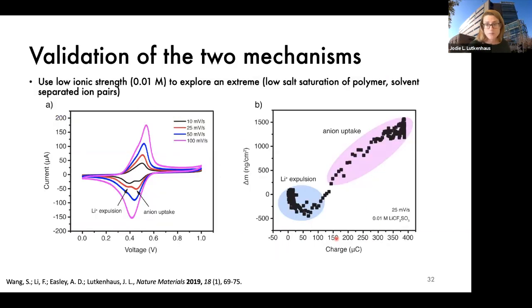There are a few different situations that can be going on, and I haven't even begun to talk about the idea of solvent transport. So to get a better idea of this mechanism, I asked my student to go to an extremely low concentration where we can consider the electrolyte to be solvent separated, so there's less chance of contact ion pairs or ion clusters transporting in. That simplifies the picture, and through that, we're actually able to see features of both of these ion transport mechanisms. So this is the CV for the low concentration case.